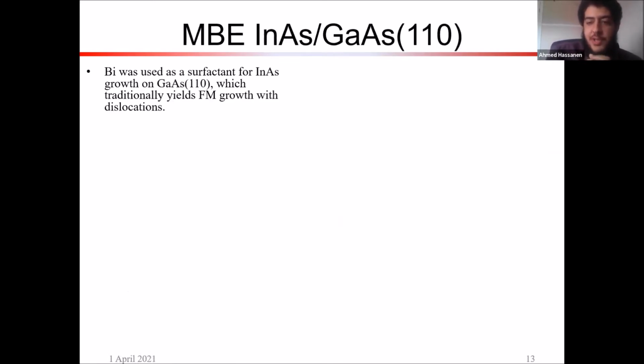This is just a bit of literature review here. We can see that bismuth as a surfactant has already been used on the 110 surface for indium arsenide on gallium arsenide growth. So this isn't homoepitaxy. This is growing indium arsenide on gallium arsenide. And gallium arsenide on 110, when we're growing it, also proceeds in a 2D growth. We want to be able to use the SK growth mode on it to get quantum dots.